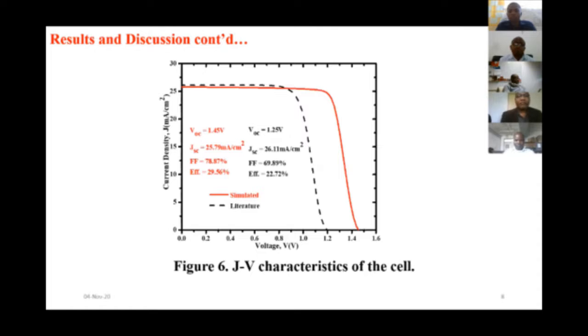And with this, we tried to investigate the JV characteristic of our cell. The red one is from our simulation, and the black dotted one is what we got from the literature, the layer parameters from the literature. We realized that with 100 nanometer FTO, TiO2 of 50, and absorber layer of 300, it gave us a significant improvement of the efficiency of the cell from 22.7 to about 29.56.